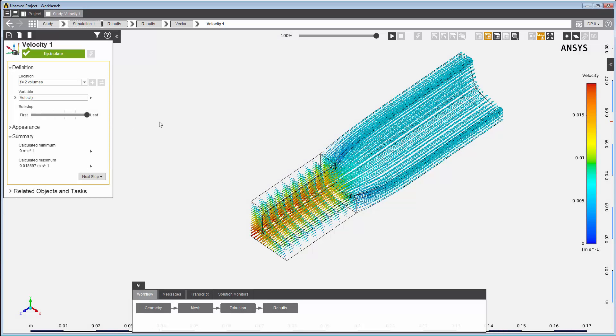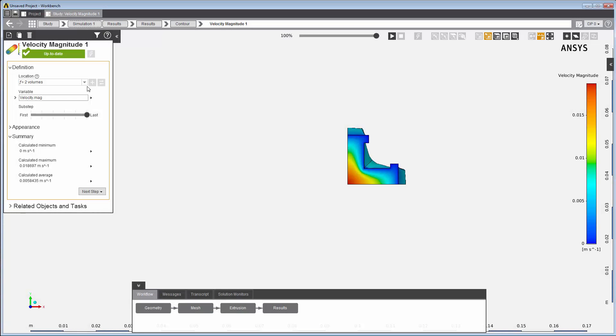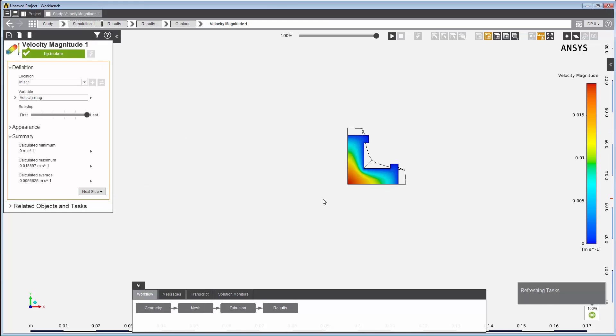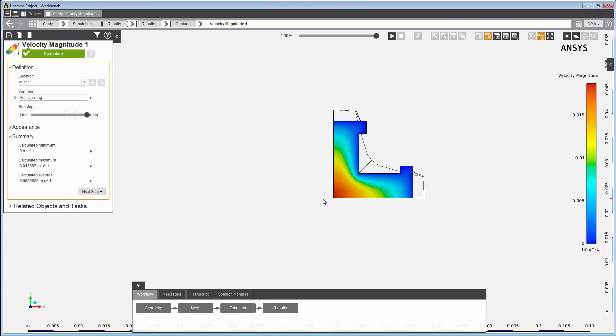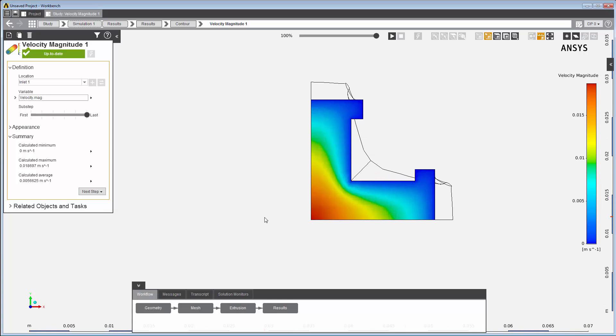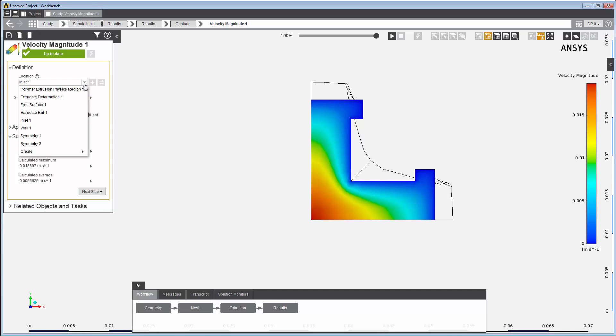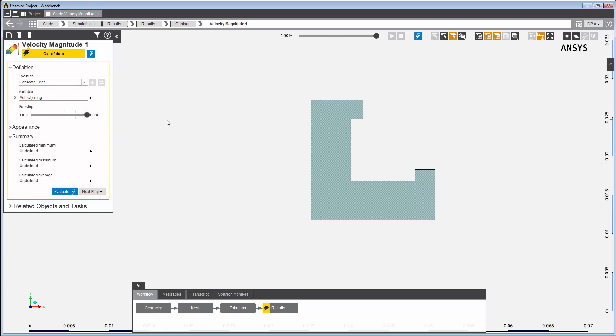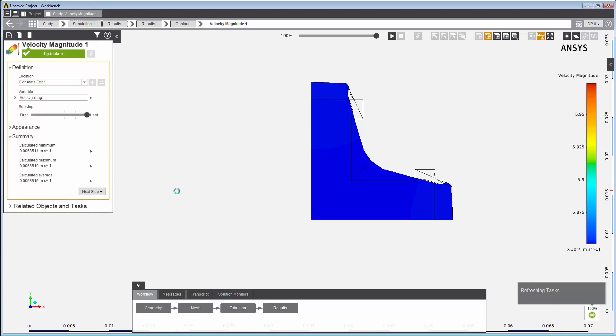The vector result illustrates the velocity vectors in the flow field. Here, we use the velocity contours on the inlet and the extrudate exit surfaces to compare the initial shape of the die and the extrudate with the final shape of the extrudate. The final cross-section of the extrudate is significantly different from that of the die, due to the velocity rearrangement that occurs at the die lip. Within the die, the velocity is higher at the center of the channel, while it must be constant in the extrudate where no force is applied. The redistribution of matter induces deformation.